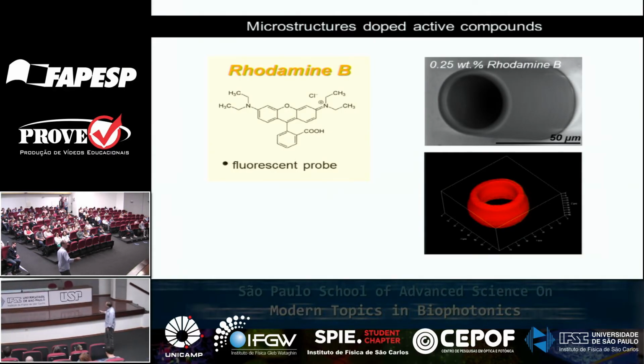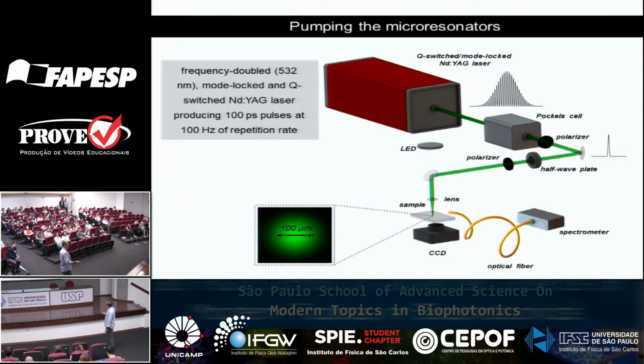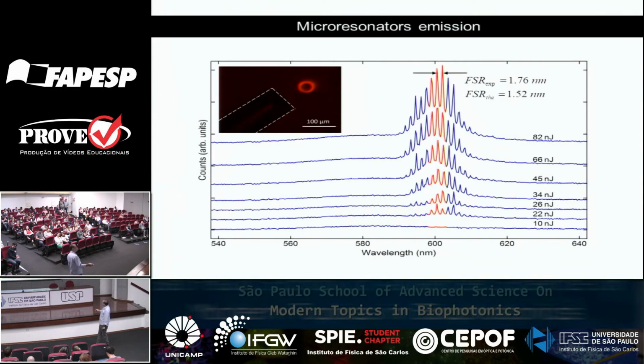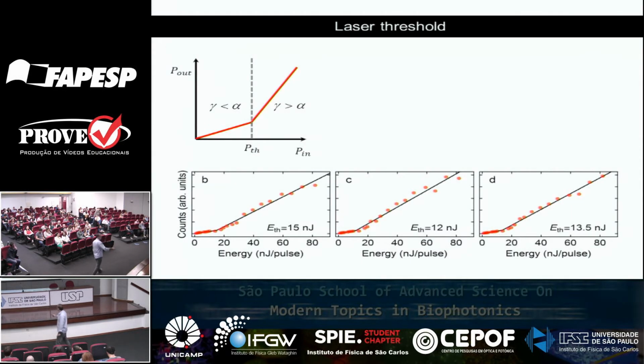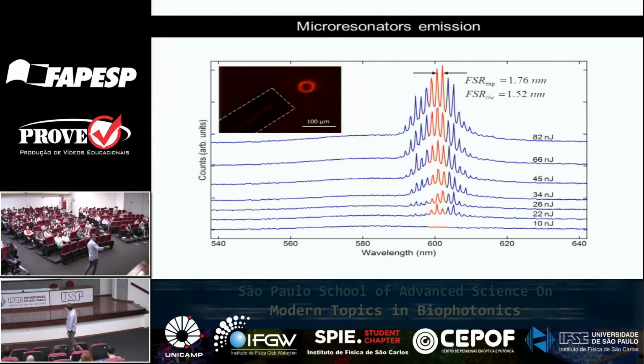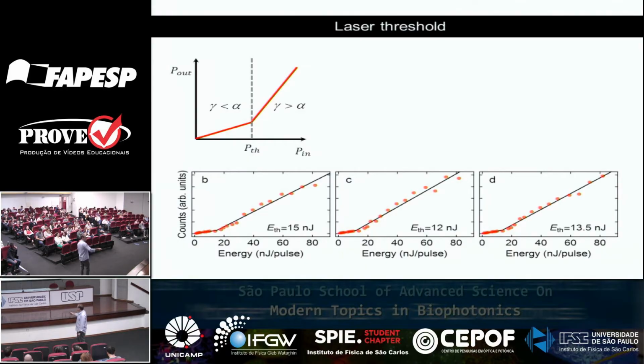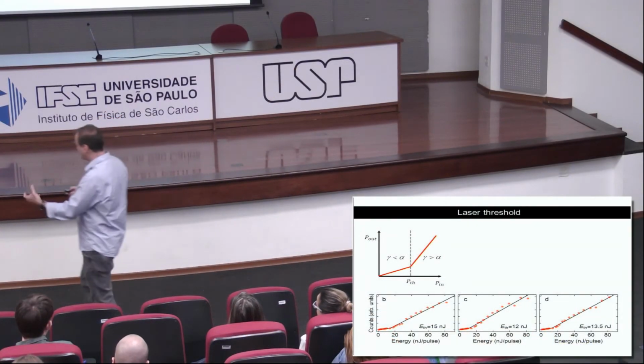We can have now in our polymer rhodamine B, which is a fluorescent dye. And in this case, we can excite our microstructure with a Q-switched mode-locked laser, as I mentioned before, in the green. So I have here my microstructure. I use this laser to excite the microstructure containing the rhodamine B, and then with an optical fiber, I can collect the emission, and then you see laser emission. So those are the modes of our structures, right? That's the free spectral range here. If we only focus on those 4 different excitation intensities, and look at the intensity of those peaks as a function of the excitation intensity, you get the threshold curve which is expected for laser action. So we were actually able to fabricate micro-ring lasers using two-photon polymerization.